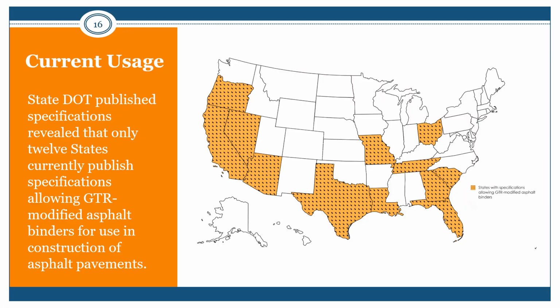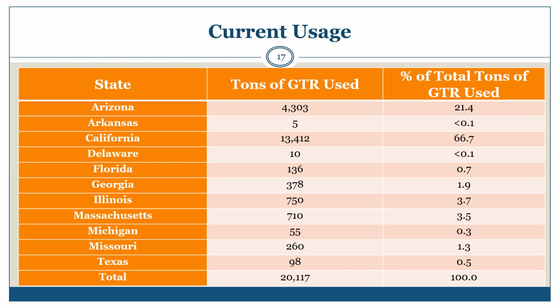As of July 2021, a review of state DOT published specifications revealed that only 12 states currently publish specifications allowing GTR modified asphalt binders for use in construction of asphalt pavements. The National Asphalt Pavements Association recently reported that 21 producers from 11 states indicated using GTR in some asphalt mixtures. The 20,000 tons of GTR used, reported by NAPA, is about 17% of the 119,000 tons of GTR reported by the U.S. Tire Manufacturers Association to be used in modified asphalt binders.